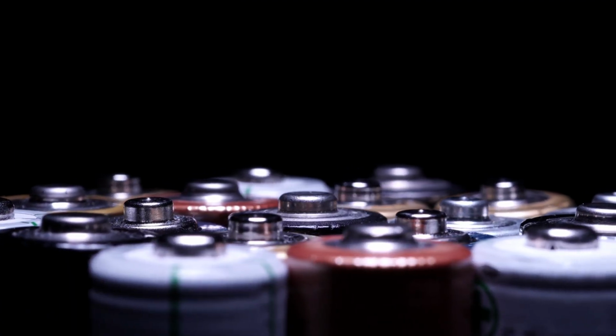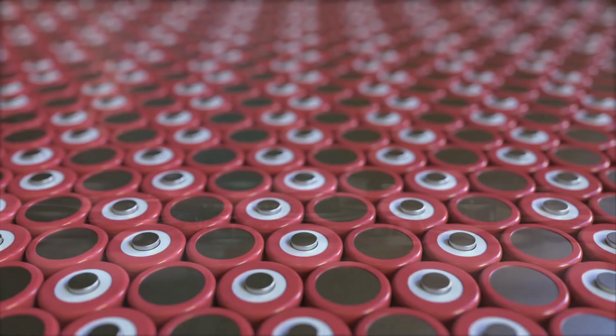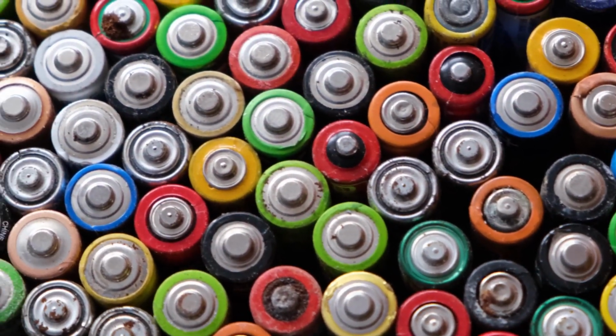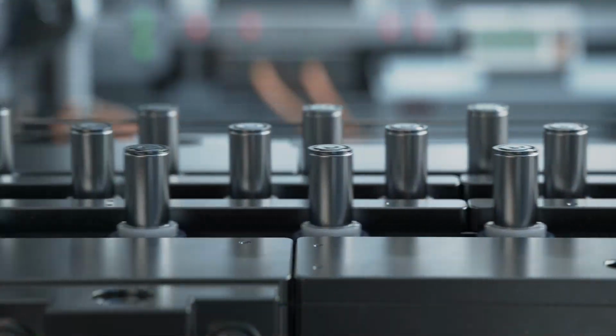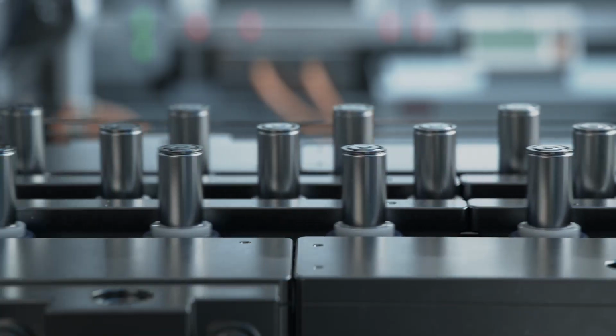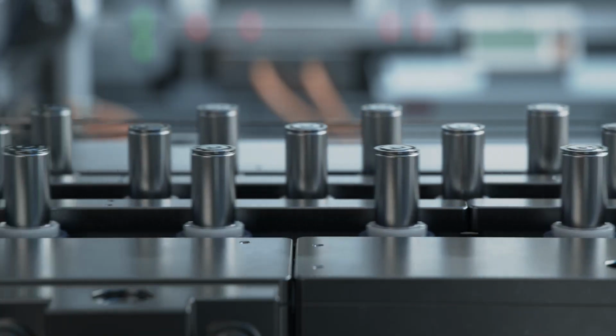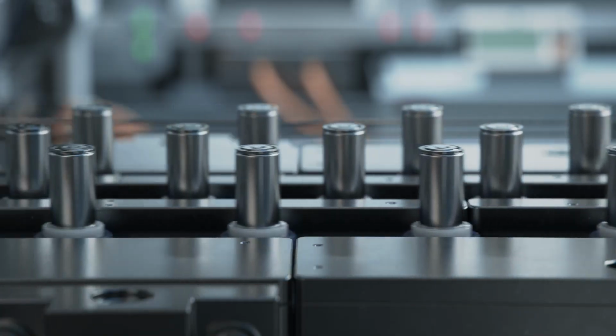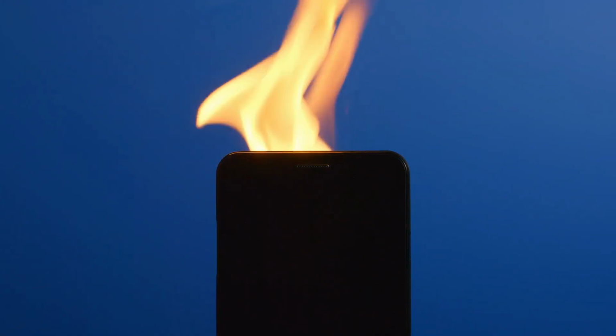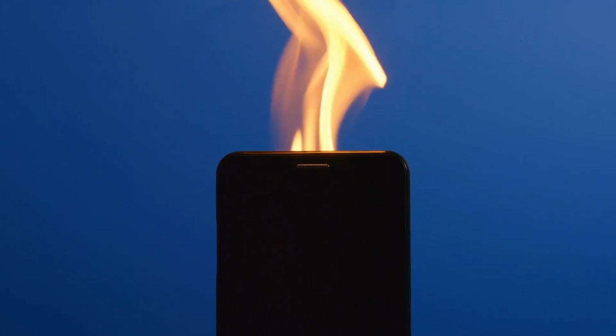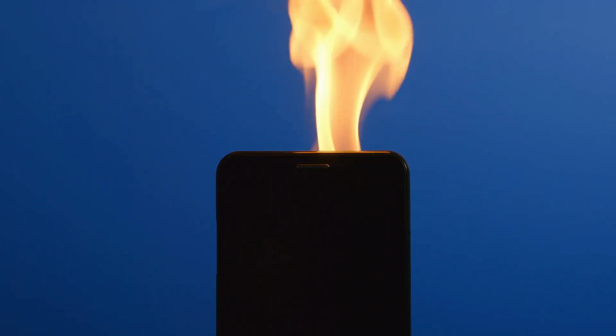But the layers inside a battery don't stay perfect forever. Here's an electrode from a new cell compared to one from an old one. You can see lithium building up in the wrong places. If this degradation gets out of hand, we get a catastrophic failure. We're simulating that by pushing this cell past its breaking point. It starts around 80 degrees Celsius, when the protective layer on the anode breaks down. The reactions release more heat, and if that heat can't escape, the temperature keeps rising into thermal runaway.